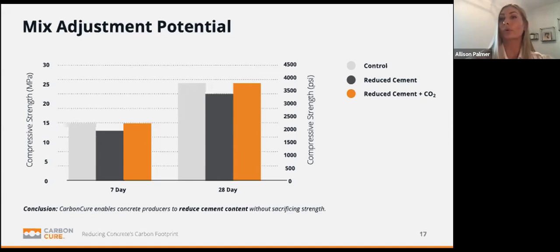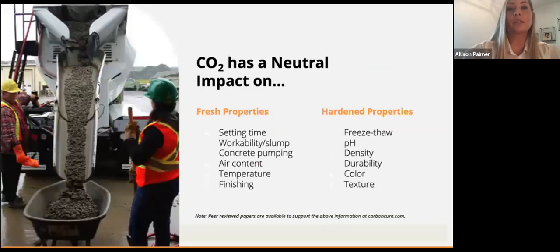QC team works really closely with our technical services team to figure out how much they can adjust a certain mix and how much cement they can take out while maintaining the same historical strength. So the addition of CO2 and reduction of about 5% cement has no impact on the fresh or hardened properties of the concrete. In fact, if we didn't tell you CO2 was being used, you would not be able to tell.